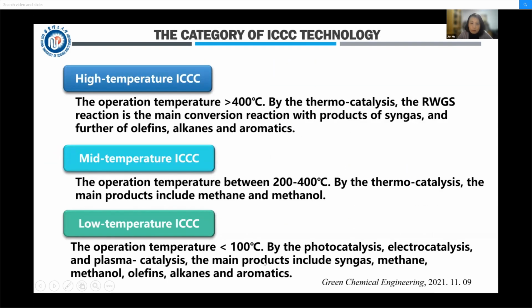And for low temperature ICCC, when the operating temperature is lower than 100 degrees C, such as flue gas after desulfurization from the power station, we can introduce photocatalysis, electrocatalysis, and plasma catalysis to obtain different desired products. So that is the different kinds of ICCC depending on the flue gas temperatures and operation temperatures.